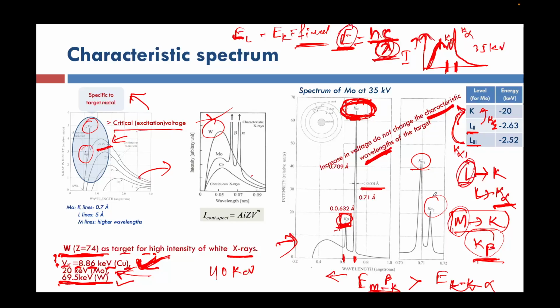So that is why when we do an analysis or an indexing of an X-ray diffractogram, we always strip K alpha 2 using some commercially available software, right? So there is always an option of stripping K alpha 2. That means after that, we will only get the spectrum corresponding to K alpha 1. Okay, so this is all about the characteristic spectrum that we will be getting from our anode material.